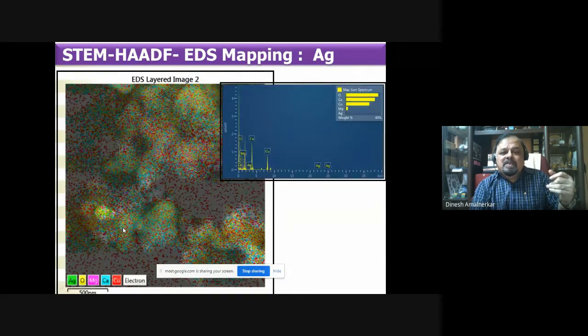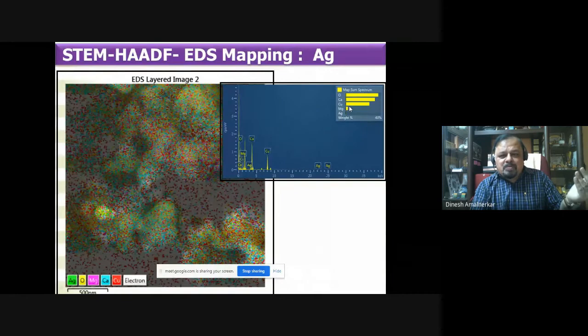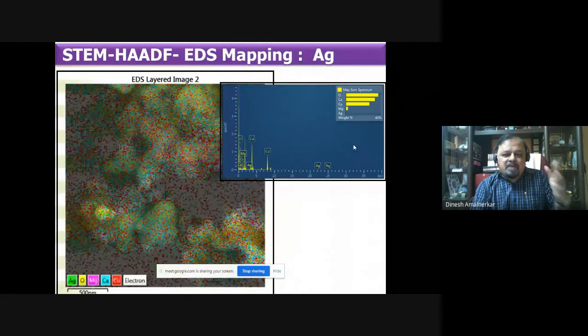Again, this is the EDAX data. Oxygen is the main component. Just earlier case it was 48%. In this case, this is a little less than 40%. Followed by oxygen, there is calcium, then copper. Again, the source is unknown, whether it is the grid or whether it is Dr. Bendale's material. We don't know. Magnesium, silver, and this is all weight percentage we have done. So we could confirm the presence of